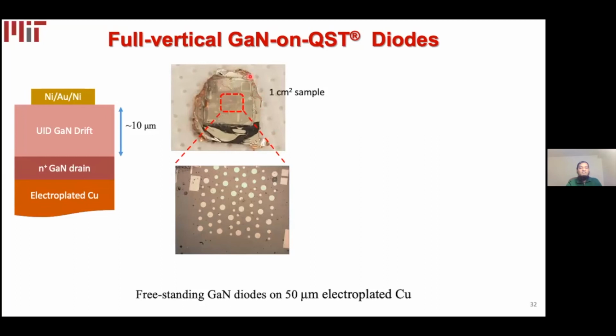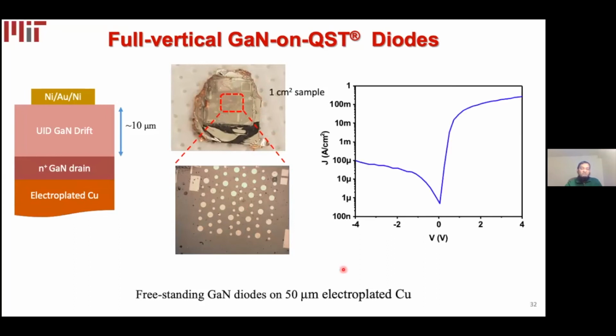Here we have freestanding gallium nitride Schottky diodes fabricated on 50 micron copper. If you zoom in, we can see the diode patterns all over the surface. And as it happened yesterday, we measured our first fully vertical Schottky diode after substrate replacement in the lab. This is the typical IV characteristic of the fabricated Schottky diode, freestanding gallium nitride from a QST substrate on 50 micron electroplated copper. We'll need to improve the device characteristics further by advanced engineering, but this is a promising start for our fully vertical devices.